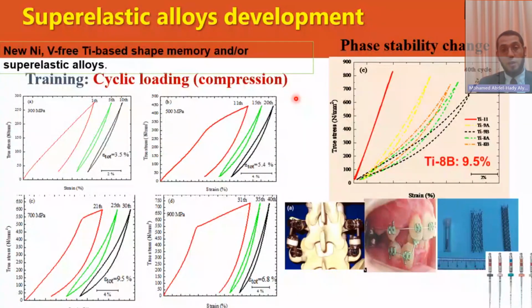Okay, let's move on. A super elastic, high elasticity material is very important in the biomedical field, especially for stents or dental applications like teeth crowding. This wire should be a very highly elastic one. So we developed another alloy that's very highly elastic. This is a stress strain curve, right? If we stress the material and unload the material, how much strain is recovered, how much strain is permanent? You can see we do cyclic loading. We load and deload the alloy and see how much strain can be recovered. So we can see that the material, which we call a super elastic alloy for stent and wire production, by training the alloy, we can achieve very high elasticity.